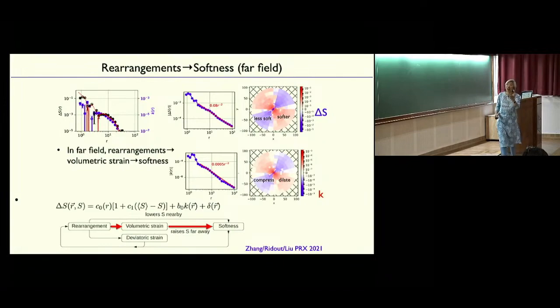Okay, so now I can look at the change of softness. Let me look at the change of softness as a function of distance away from the rearrangement. If I look at the change of softness, it decays like 1 over r squared, and it has this dipolar form. It's more soft where it dilates, and it's less soft where the system is compressed, according to the volumetric strain dipole, okay? So that tells me the softness in the far field is proportional to the volumetric strain, the change of softness has a piece that's proportional to the volumetric strain. But it's different from the volumetric strains. The volumetric strain is here in blue, okay? The change of softness is black. You see the two are different if I'm close to the rearrangement.